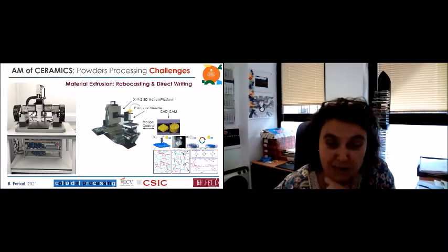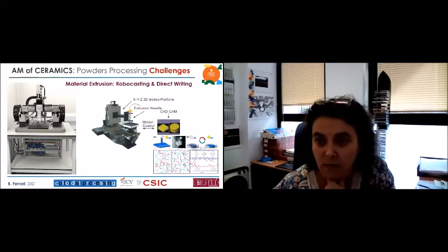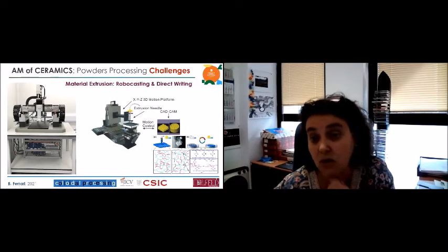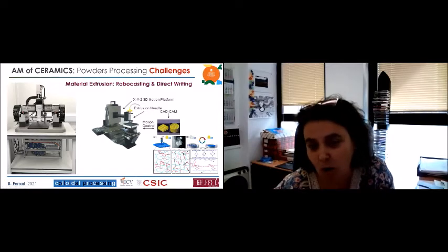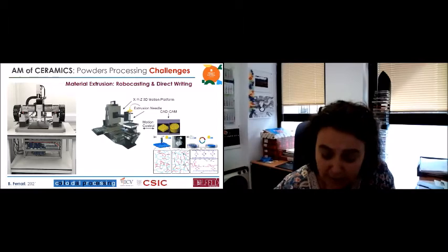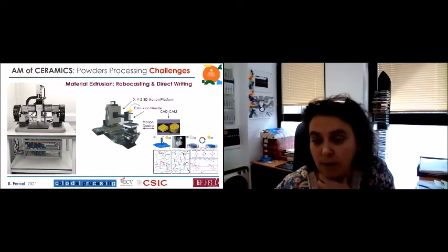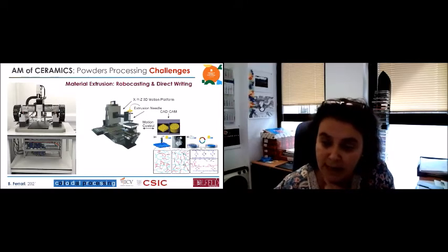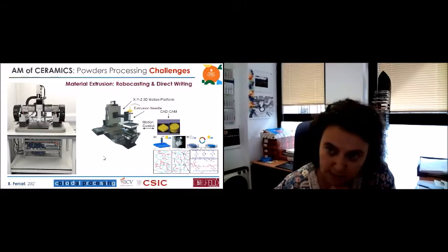Robocasting is pressing paste, so you need a lot of pressing in, and in direct writing you are pressing ink, so the pressure is not so high. Here we left all the work to the chemistry of the ink, which should gel by the time it passes through the nozzle to maintain the next layer, right? So it's very hard work to work with these gelling inks, right?